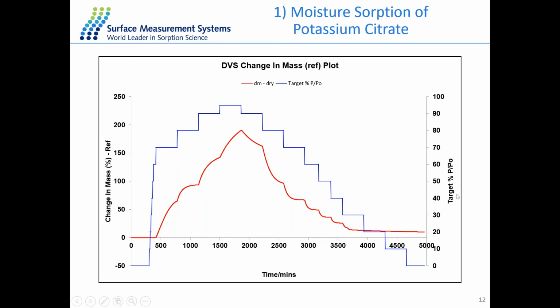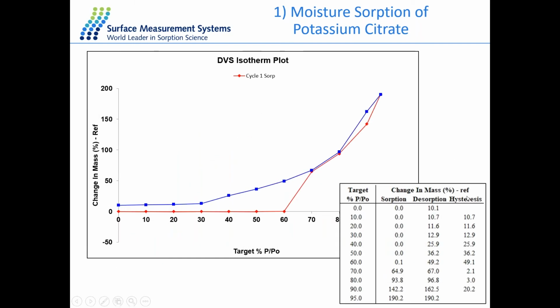mass and plotting against the target partial pressure or relative humidity. And then we can get this water isotherm for the experiment. And this report is just giving you the equilibrium mass change at different humidity steps, as well as the hysteresis between the sorption and desorption.